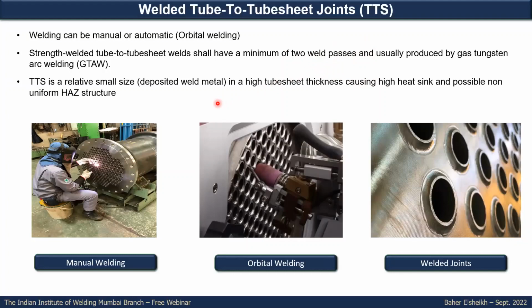One of the challenges while doing the welding of the tube-to-tube sheet joint is the relatively high thickness of the tube sheet. You will have a high heat sink, which will cause a high reduction in the temperature during the application of the weld. That's why in materials where you need to maintain interpass temperature to avoid any issues, like the recommendation for some materials, in such cases you might need to apply preheat, and this preheat should be applied uniformly on the tube sheet. Otherwise, you might have an issue in the ligaments area in some thin tube sheets. And this will be a very big challenge if you are working in the after service for repair or doing some activities in the tube sheet.